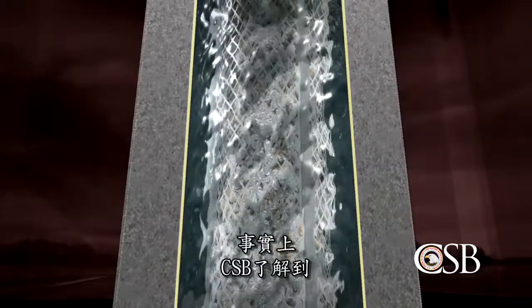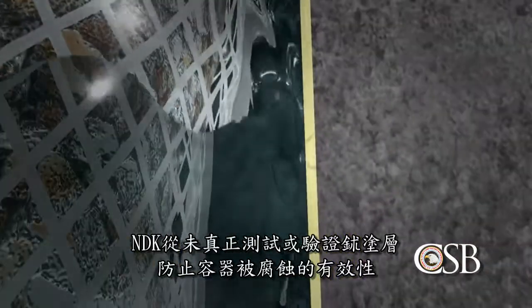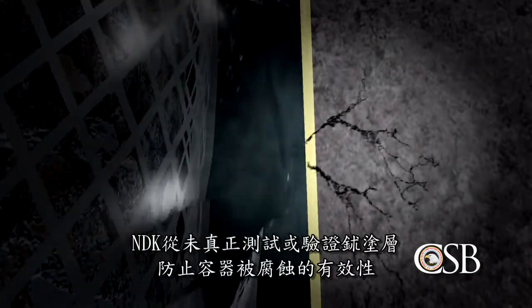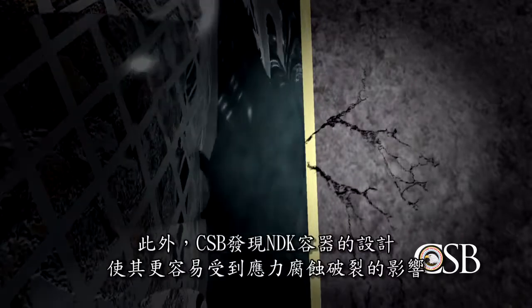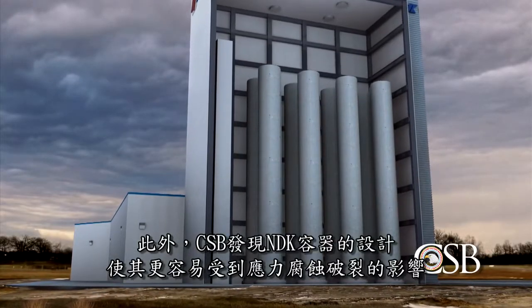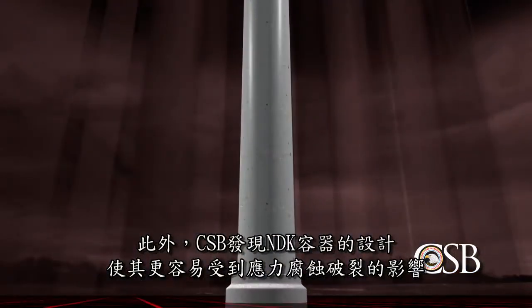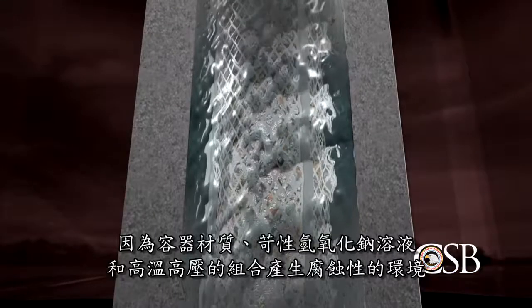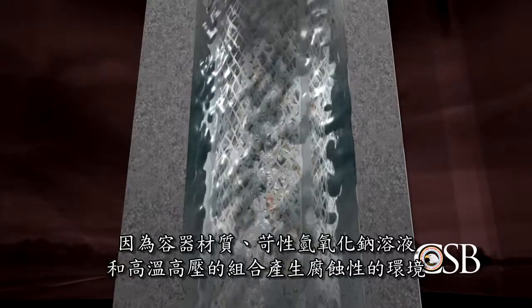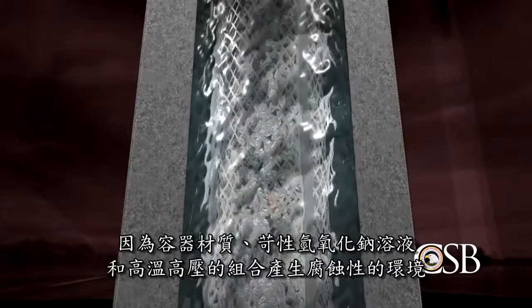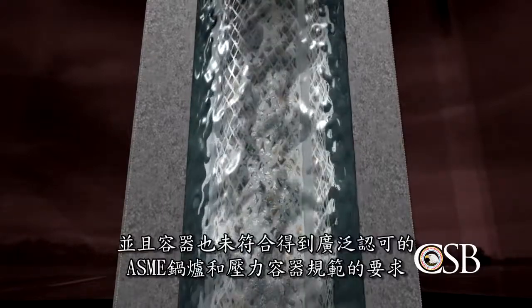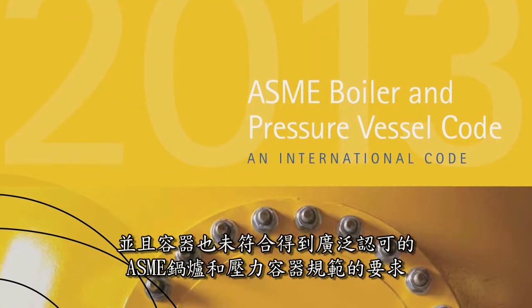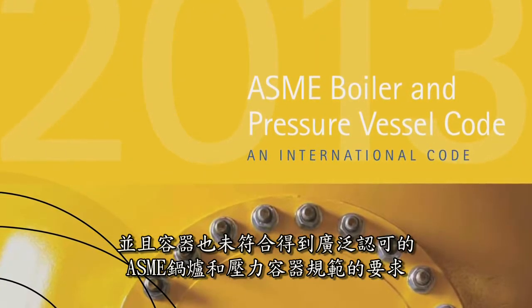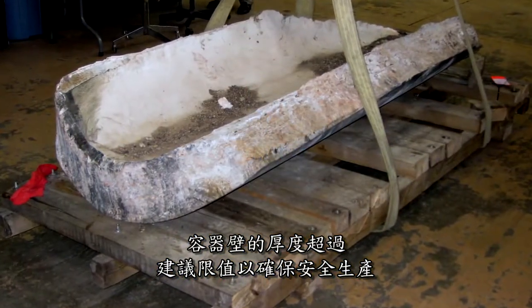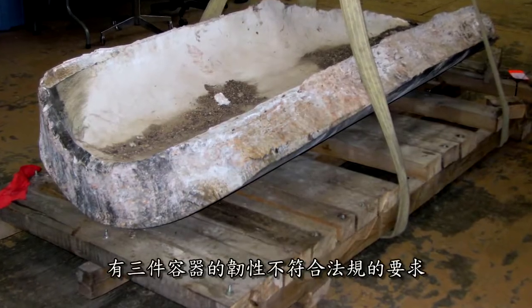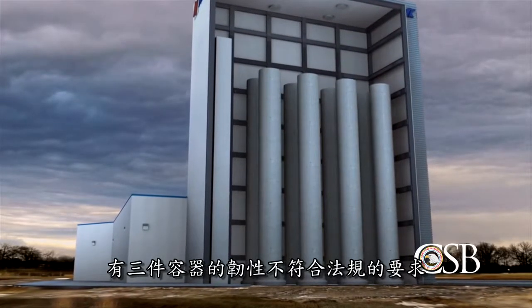In fact, the CSB learned that NDK never actually tested or verified the effectiveness of the acmite coating to prevent the corrosion in the vessels. In addition, the CSB found the design of the NDK vessels made them inherently susceptible to stress corrosion cracking. A combination of vessel materials, caustic sodium hydroxide solution, and high temperatures and pressures created a corrosive environment inside the vessels. Also, the vessels did not meet requirements of the widely recognized ASME boiler and pressure vessel code. The thickness of the vessel walls exceeded recommended limits to ensure safe manufacturing, and 3 of the vessels did not meet the code's requirements for toughness.